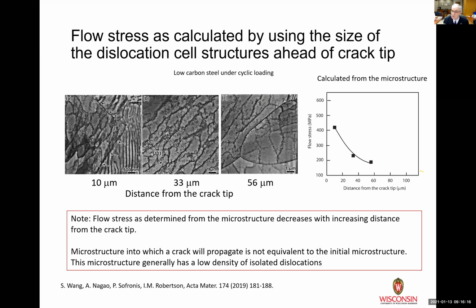We then took samples at different distances, at 10 microns, at 33 microns, and 56 microns from the crack tip. And we said, okay, what does the microstructure look like at those distances from that crack? And you see the difference, right? You can see sort of very detailed, smaller cell structure at 10 microns. You still have a cell structure at 33 microns, and you still have one at 56 microns, but the cell size is much bigger at 56 than it is at 10. And at 56, you can get the idea that there's still individual dislocations within the cell wall. And this is what you would expect, right? More deformation close to the crack tip. You're seeing that in the smaller dislocation cell size.